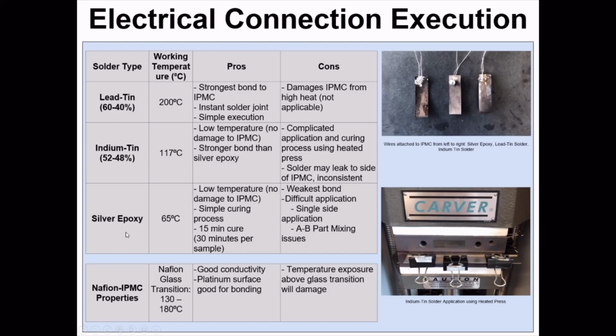So that led us to silver epoxy. And silver epoxy was okay. That's the best way I could describe it. It was an A and B part mix. It was really difficult to put on. It was an oven cure, and it often broke. It was a really, really weak bond to the surface.